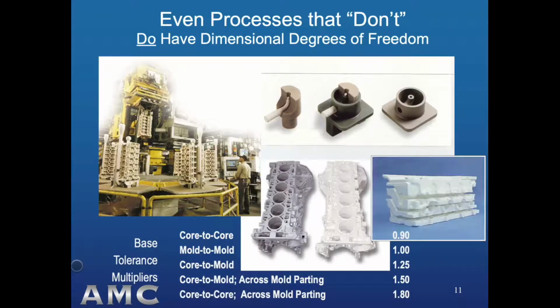Here are two of the most accurate mold cavity making processes. First, the investment casting process. Here we see the wax pattern, but it has a ceramic core here, another ceramic core, of which there is another piece that sits in here. Part of the ceramic core assembly in the green wax is shown there, and there are degrees of freedom in the assembly of those ceramic cores and match lines where those ceramic cores join together.